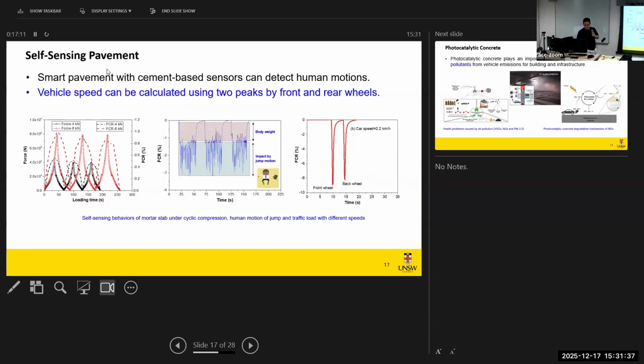Based on the results, we found that the self-sensing behavior is stable under cyclic compression. Secondly, under sudden impact load, the FCR peaks are generated, and these fluctuations are related to the jumping height and the gravity of the human body. And finally, the vehicle speed can be calculated from the two FCR peaks induced by the front and the back wheels. So we can say the smart pavement can provide real-time monitoring of infrastructure health and detection of traffic conditions. Based on this information, we can detect the traffic weight, the traffic speed, and the traffic density. We can get all this information.